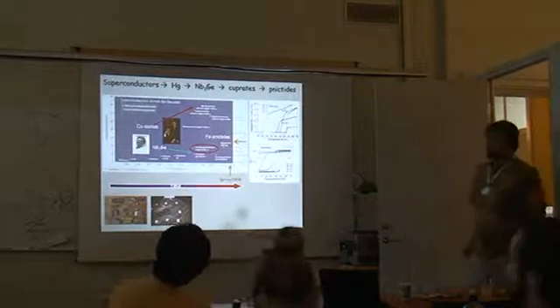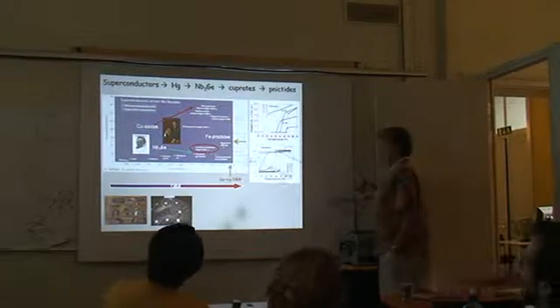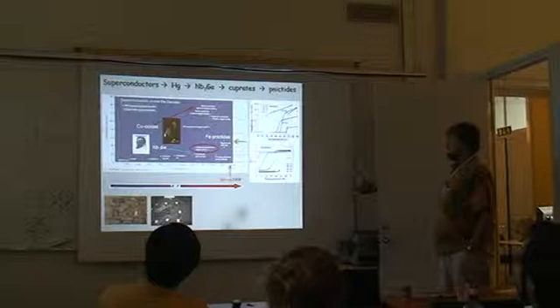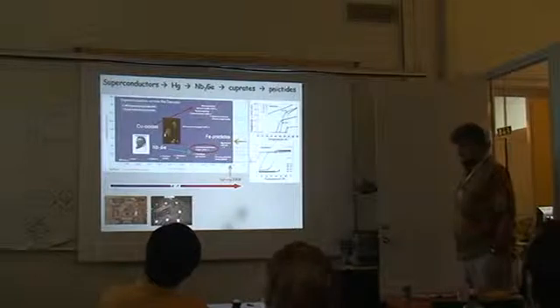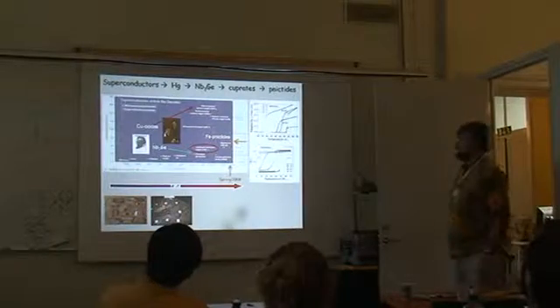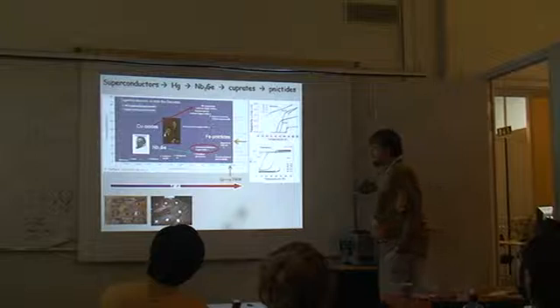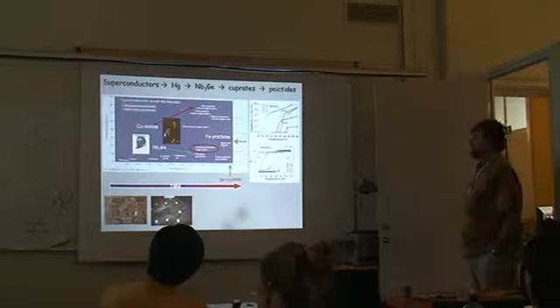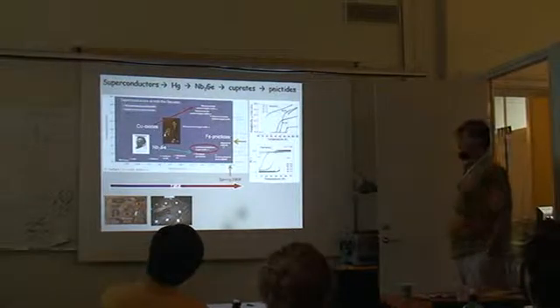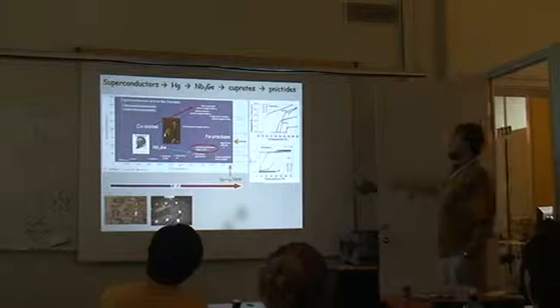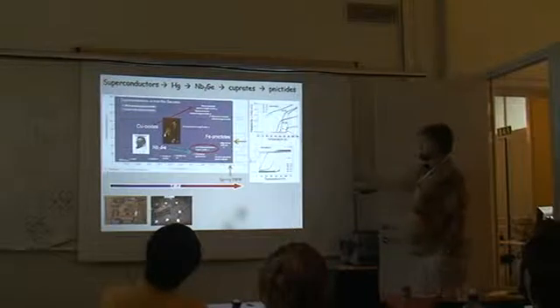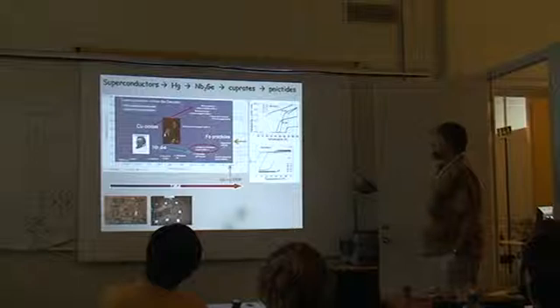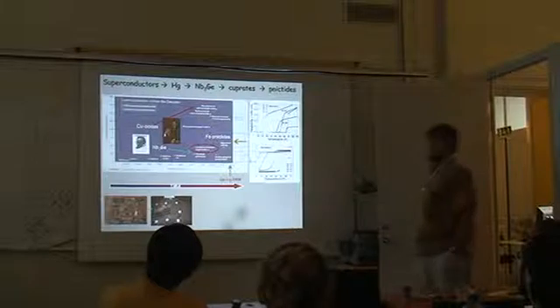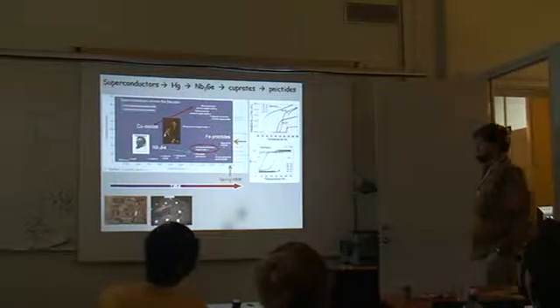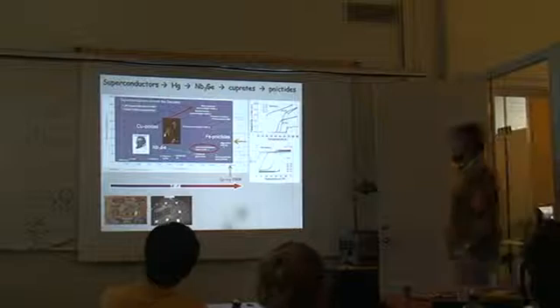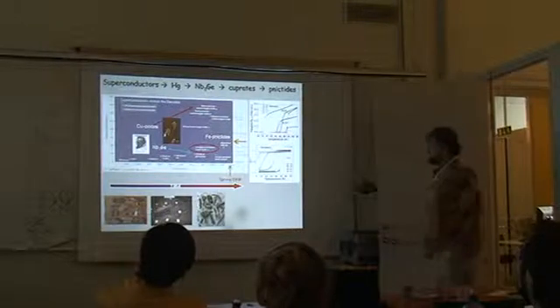Finally, in 2006, there was a discovery of a superconductor of this iron-based family at 7 Kelvin. Then the same group of Professor Hideo Hosono at Tokyo Institute of Technology pushed the transition temperature in this system to 26 Kelvin. And then finally, by spring of 2008, we had 58 or so Kelvin in the iron arsenic class of these materials. And that's, of course, where tremendous excitement started. And this brings us to the Iron Age.